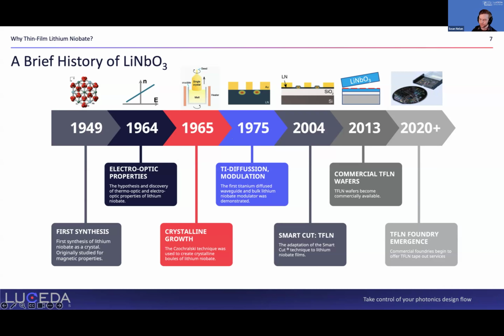A bit then on how bulk lithium niobate compares to thin film lithium niobate and why thin film lithium niobate is so special. Bulk lithium niobate, of course, used since the 70s, is a great medium for high-speed modulators. Bulk lithium niobate modulators operate up to 300 gigahertz, and this is a great system to achieve high-speed operations for telecom and datacom applications. But a bulk lithium niobate waveguide and a bulk lithium niobate modulator is pretty big. These are on the order of 5 to 10 centimeters long. And if you think of a photonic chip, you're operating on the order of 10 millimeters. So we can't fit these on a photonic chip with other components. These are generally coupled to fibers on each side and implemented in perhaps a free space optic system.